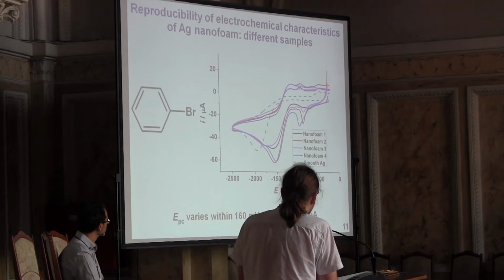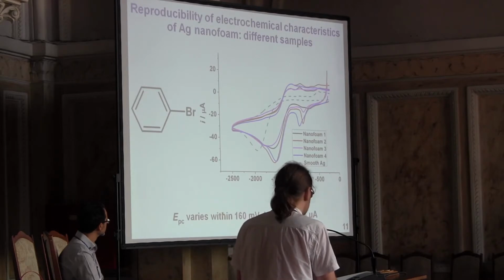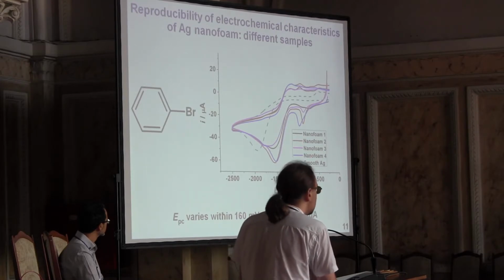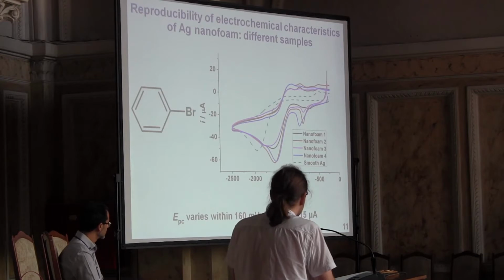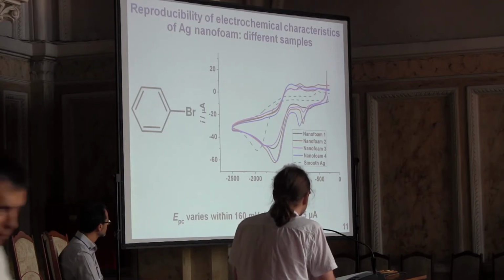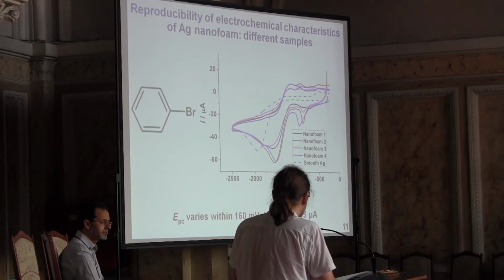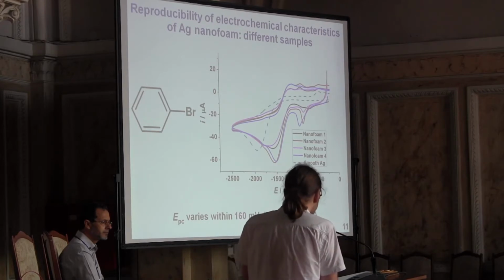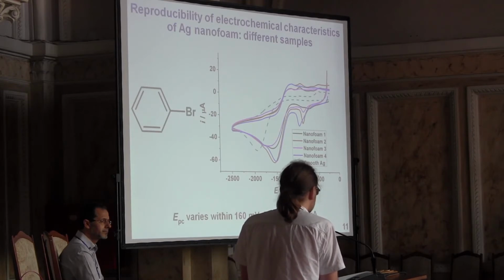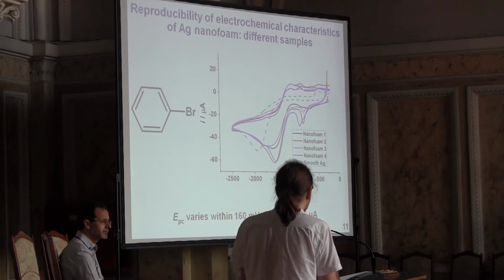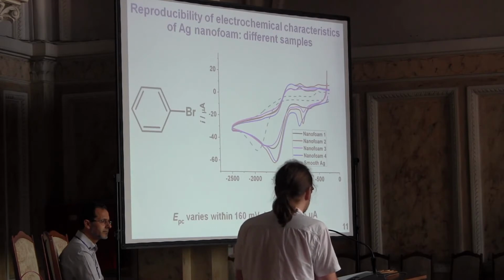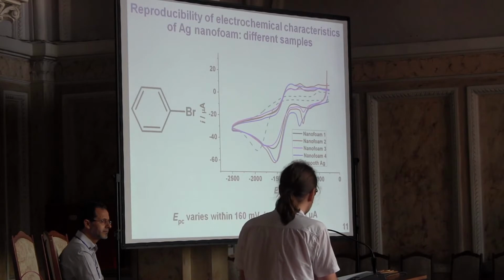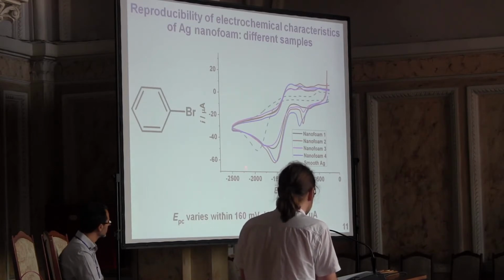Comparison of cyclic voltammograms of different samples of silver nanofoam prepared by the same method in the same conditions revealed moderate reproducibility of the characteristics of the reduction process. Despite this, we should emphasize that the superior performance over the smooth silver is statistically significant.